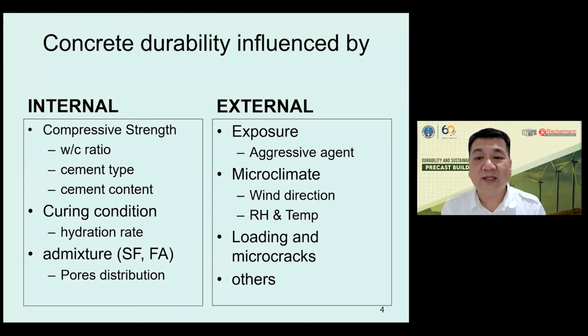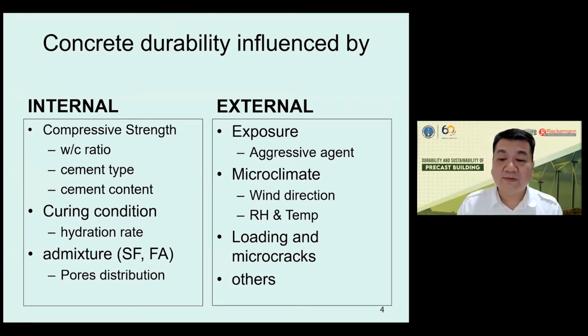This is a very complex interaction. While for the internal factors, it is mainly the compressive strength, because compressive strength shows a high performance in durability. So we can have a good quality concrete with high strength, and then we have good durability. But also during construction, we can improve the durability by providing good curing conditions and also using some kind of admixture.